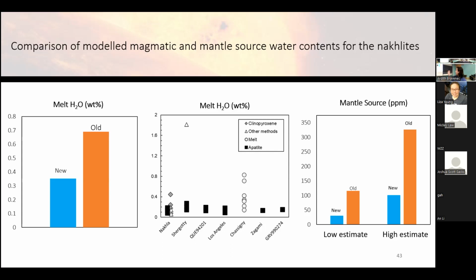And then finally, we can back calculate using those different models the complete mantle source water, taking into consideration different crystallographies, different minerals, and different melting models. And sure enough, the new water contents are significantly lower than the old, probably ranging from around 40 parts per million up to perhaps a little over 100.